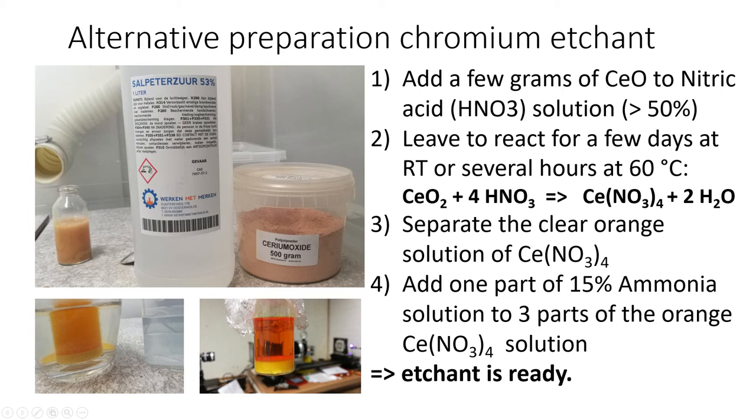I couldn't find a cheap supplier here in the Netherlands, so I used a trick to make it myself. The material that I did have in my workshop was cerium oxide, which is cheap and also widely available as a polishing agent for glass. I added a few grams of cerium oxide to a concentrated solution of nitric acid, about 53%.